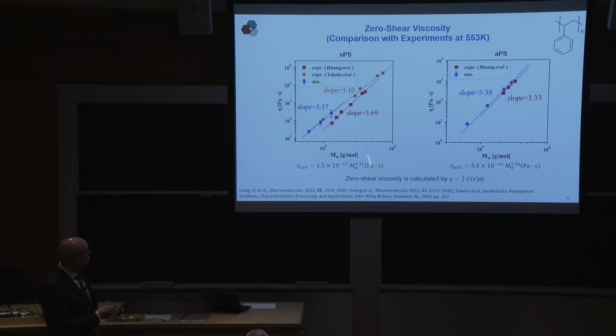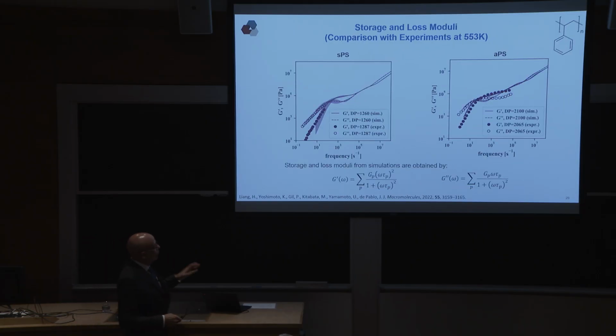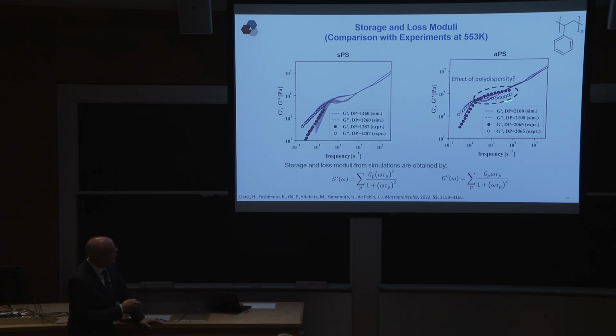Now, this is all data that you have to find in the literature, so you do not always have all of the characterization of the samples. You don't really know what the polydispersity is. But the fact that, for the most part, the points for the experiments and the calculations are on the same plot is very, very encouraging. All right, so the moment that you start to analyze the data a little bit more carefully, and you look at these relaxation curves in great detail, you start to see some discrepancies. Again, the lines are simulations, the points are experimental data, and in particular, over here, you see that the agreement is not all that great.